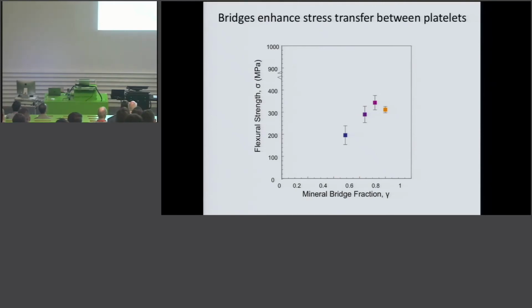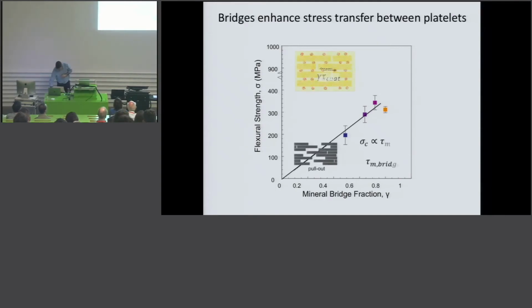And this is the final plot that I want to show you, which is a result of about 10 years of research, which shows the strength of this material as a function of the fraction of mineral bridges. So the way we control the fraction of mineral bridges is by using platelets that have a coating of titanium oxide, which will de-wet the platelet surface at high temperatures and create these little blobs in between the platelets. And the process we've developed allows us to control how many of these orange blobs exist between the platelets, and then eventually we can measure the strength of these materials.